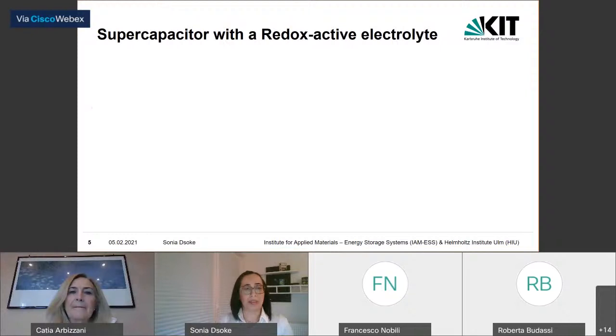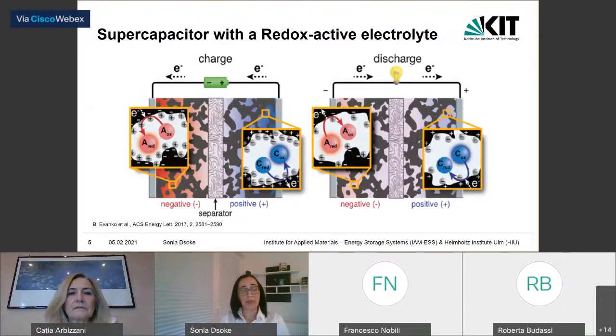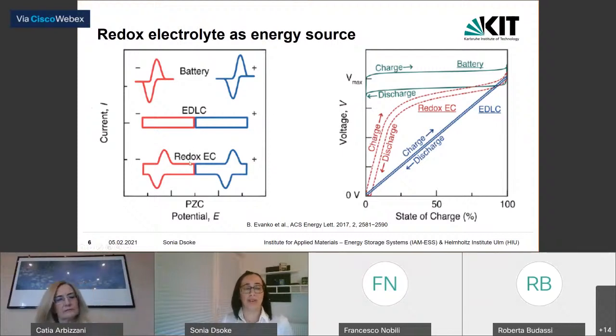First, a short background about a supercapacitor with a redox-active electrolyte. Normally you have two identical electrodes based on a very high surface area carbon, and the energy is stored via the double layer. If you have a redox species dissolved in the electrolyte, you can add additional energy storage via Faradaic reaction. The redox species will oxidize or reduce at one electrode, and another redox species can oxidize at the other electrode. So it is a hybrid system with a double layer capacitance and the Faradaic reaction coming from the redox species in the electrolyte. As a hybrid system, it shows an electrochemical signature in between a battery and a double layer capacitor.